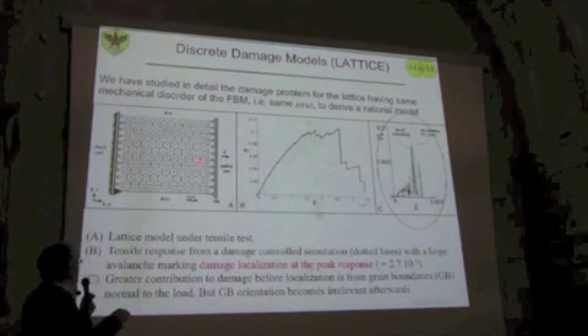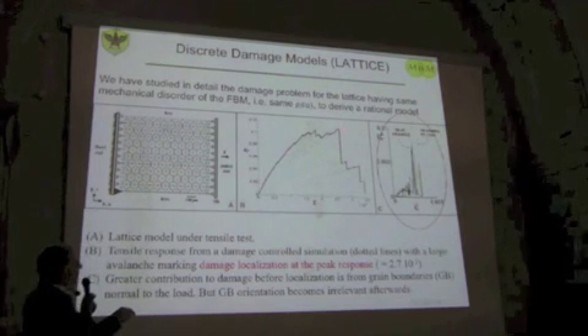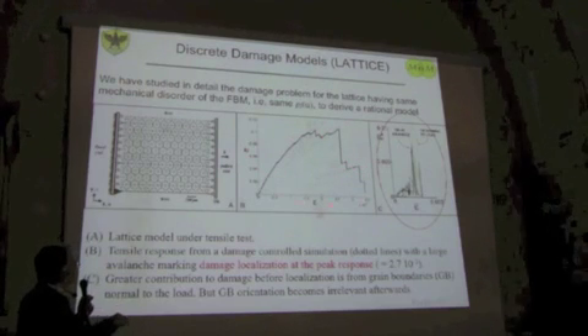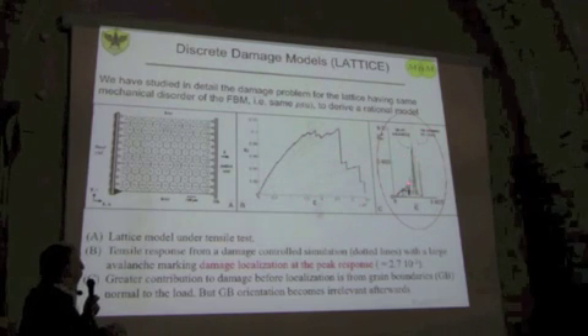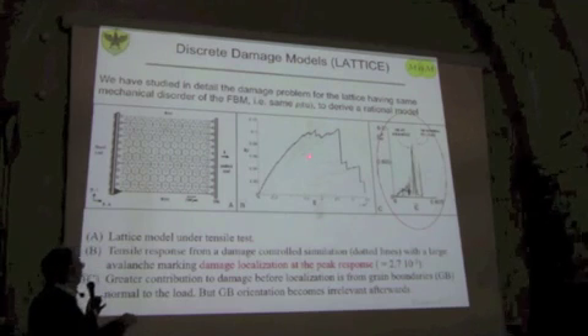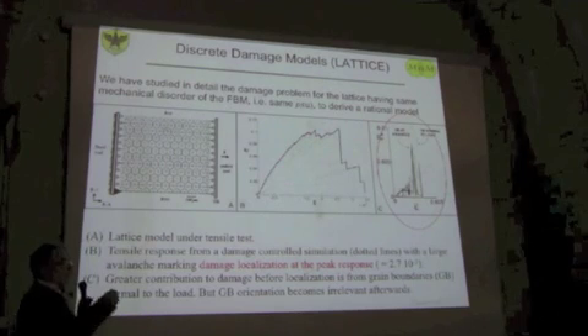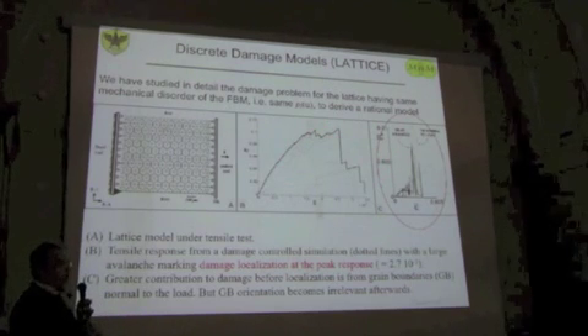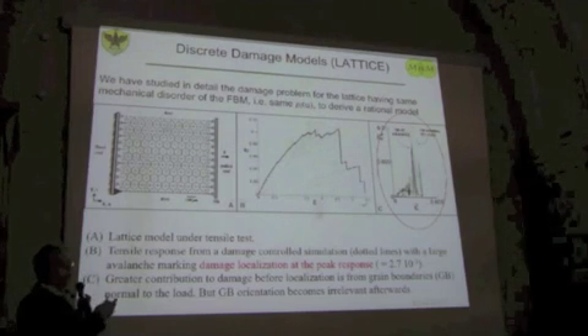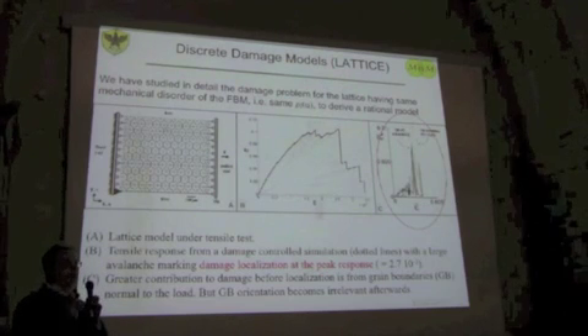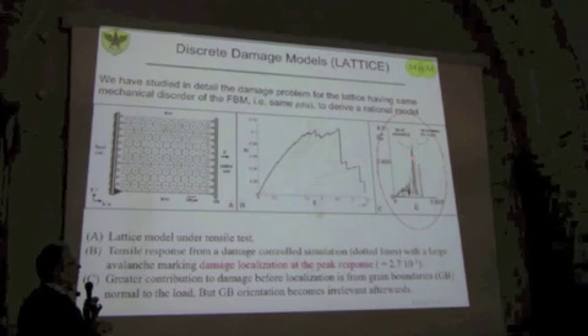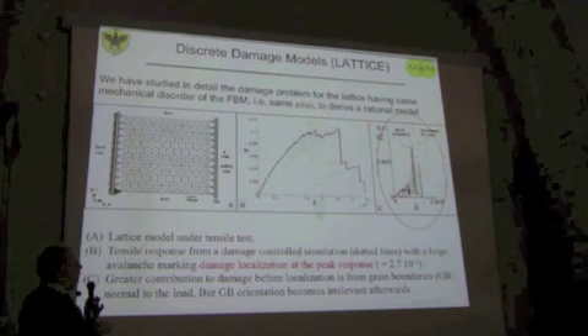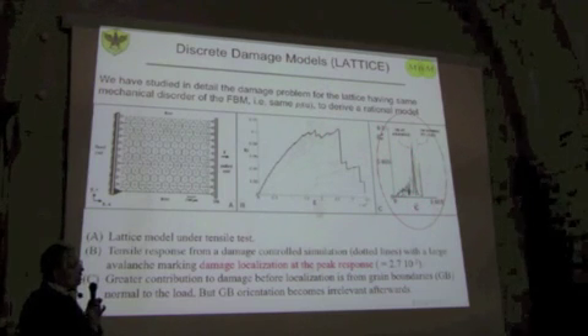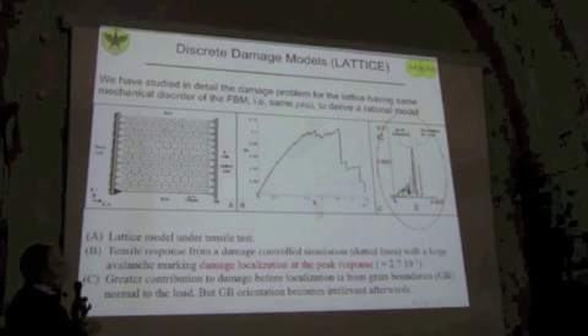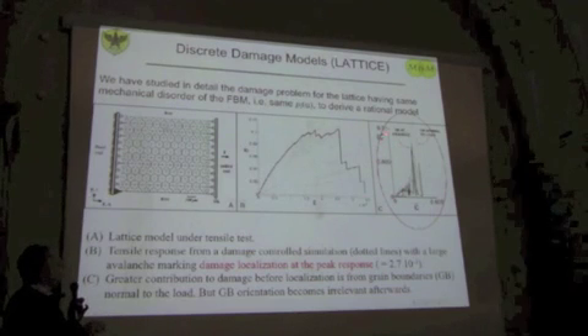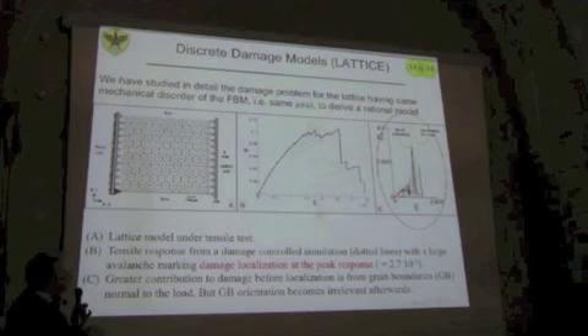Now, when you simulate a tensile or compressive test on this system, you actually get this type of response, sigma epsilon, stress strain response. But now something very interesting happens. If we try to understand why this comes about and how this relates to the microstructural properties, you have to look into microstructural quantities. And if you do simulations, and we actually wrote the code so we were able to control anything about this model, so it was a nice virtual lab, we were able to investigate properties as we pleased. You will see that as I apply a strain in a displacement-controlled simulation, of course, I will induce the rupture of springs that can sustain strain of the same order only until a certain point.